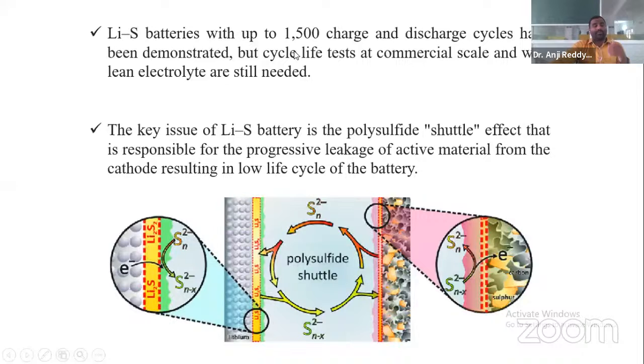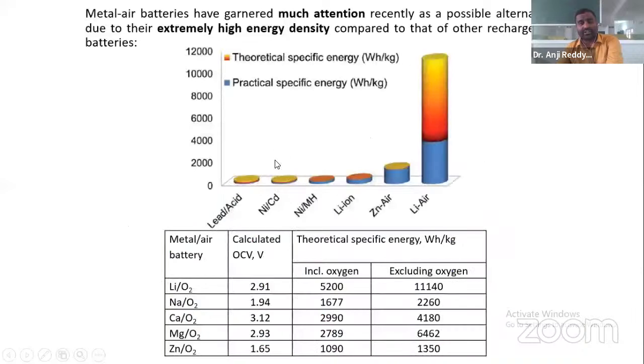At present, whatever the batteries, even lithium ion or lithium sulfur, we don't have the best electrolyte. The main key issue of lithium sulfur batteries is the shuttle effect, that is the polysulfide shuttle effect. It is mainly responsible for progressive leakage of the active material from the cathode, resulting in a low life cycle of the battery. Due to this polysulfide shuttle effect, there is a chance of leakage of that active material. This is one of the disadvantages of lithium sulfur.